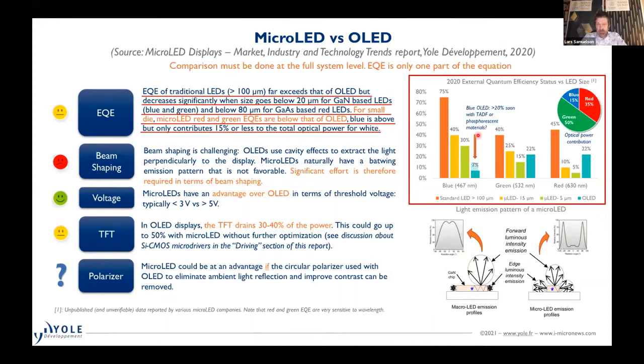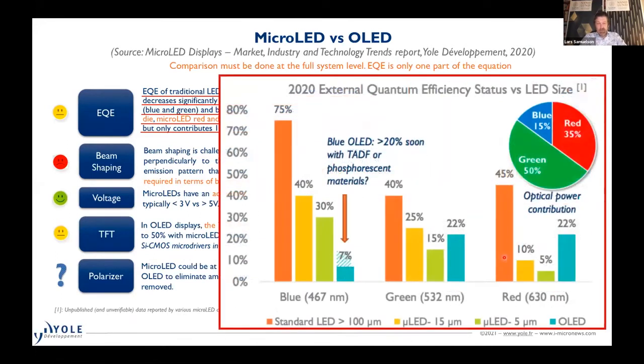This frame here is magnified here, so you can see it more clearly. You can see that the micro LEDs are doing quite well for the blue. You go from, this is more than 100, large size, 15 micron, 5 micron, still fine for the blue, still okay for the green. However, when you get to the red, things are getting more problematic. For the gallium arsenide based, you have, of course, very bright macroscopic LEDs. But when you go down to 15 and 5 microns, efficiency goes down very quickly.